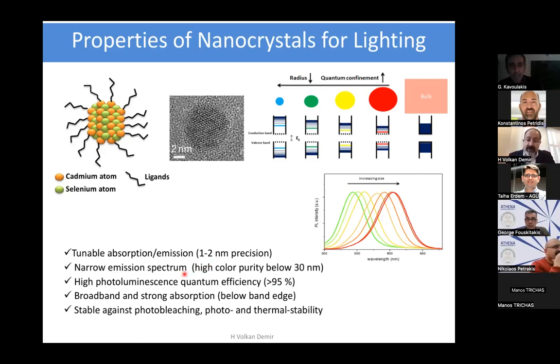Plus, with certain chemical routes, again, we can have spectrally pure emitters with full width at half maximum narrower than 30 nanometers. And some of the materials, which are typically cadmium-containing ones, have quantum efficiency more than 95%. In some cases, even near unity, limited with the precision of absolute quantum yield measurement. Obviously, this type of material is particularly critical to be evaluated for recycling purposes. However, in terms of the ppm requirement, it's actually a very low amount you use. So most of the time, it's okay to use them. However, one has to think about the recycling issue.